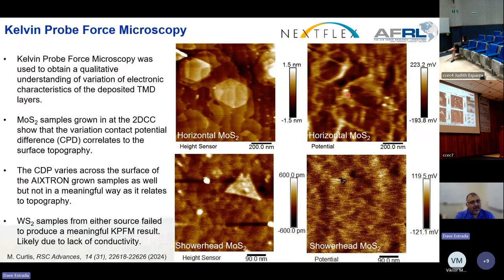You can also see it in the KPFM data. But on the showerhead reactor, we don't have very good correlation. So the surface charge is quite distributed differently for the showerhead reactor. So it may be a more defective film with more oxygen or other kinds of defects at the edge of the domains impacting the KPFM data.